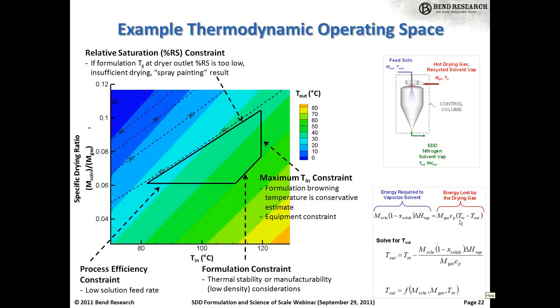The energy source is supplied by the drying gas stream, and you can think of the energy sink as the heat of vaporization required to vaporize the spray solvent. So on the left here, we're showing a graphical representation of the thermodynamic model with 4 key parameters plotted. The inlet temperature of the drying gas, the spray solution feed rate, and the drying gas flow rate. And these 2 parameters are ratioed to enable us to look across multiple scales on the same plot. It's fair to say that for a single dryer scale, the drying gas flow rate is held relatively constant. So you can think of this axis as your spray solution feed rate axis.